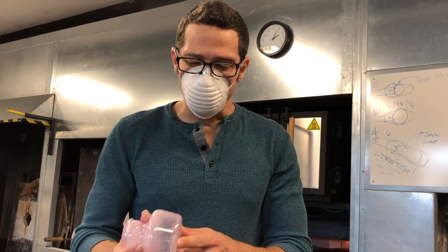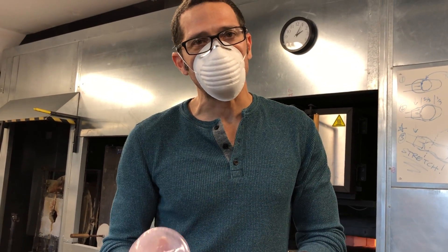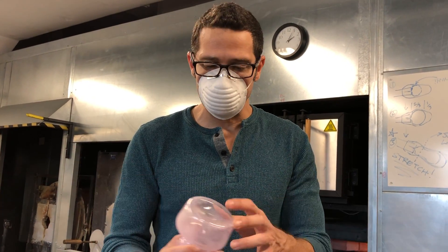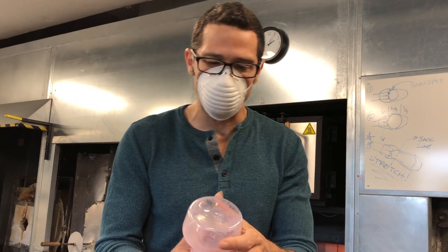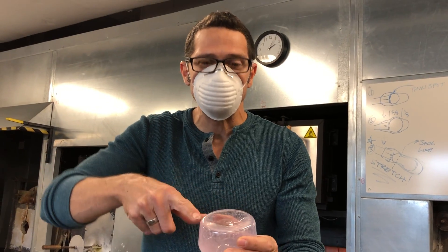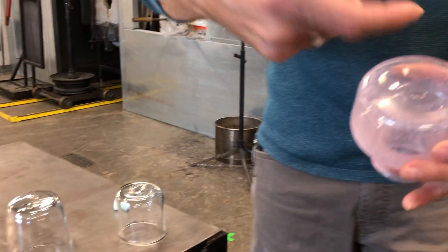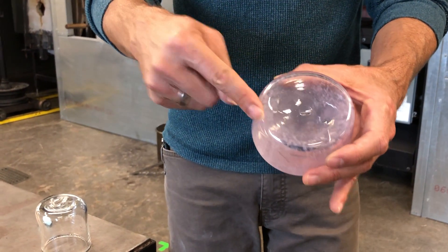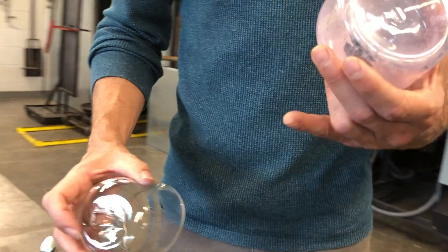When I teach intro glass blowing, my goal is for people to make puntees that they do not need to grind work off. And if they choose to torch it, it torches away really, really easily. There's a lot of things that the maker of this did to make it a successful puntee. They indented the bottom so that it would sit flat — no rocking. They matched the puntee curve with the bottom, and they matched the scale of the puntee to the size of the object. They did not accept a giant puntee for their little delicate object.